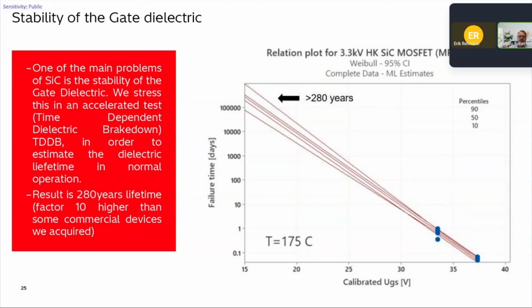Also, in terms of reliability, silicon carbide, we know the gate dielectric is a big question mark. So we do a lot of tests, so-called TDDB, time-dependent dielectric breakdown. So we subject the chip to much higher gate voltages until they break down, and then we extrapolate this type of line lifetime to the gate voltages that they will see in normal operation, like 15 to 20 volt, trying to simulate the reliability of this dielectric in real life. So a lot of work being invested into making these layers as robust as possible.